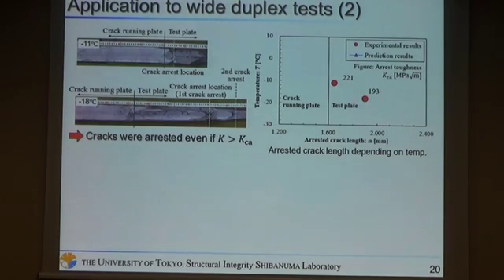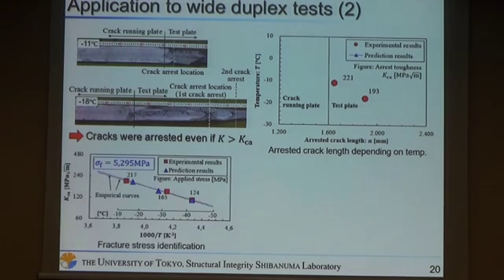These photos show the experimental results of fractured surfaces. You can see cracks are arrested even if the stress intensity factor is larger than the arrest toughness. And this graph shows the relationship between arrested crack lengths and temperatures of the experimental results. To predict these results, the fracture stress is identified like this. And the predicted results of the depth of side ligament are shown on these photos.